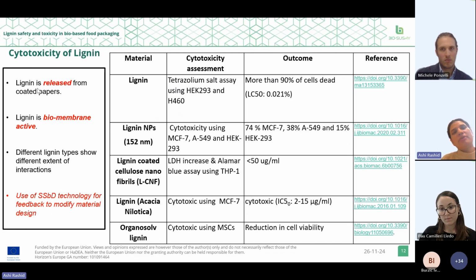From our studies, we can conclude that lignin is released from the coated papers, and the lignin is biomembrane active. This biomembrane activity depends on the type of the lignin, whether it is uncoated, unfunctionalized, or functionalized. So we have successfully shown the use of SSbD technology for feedback to modify the material design.